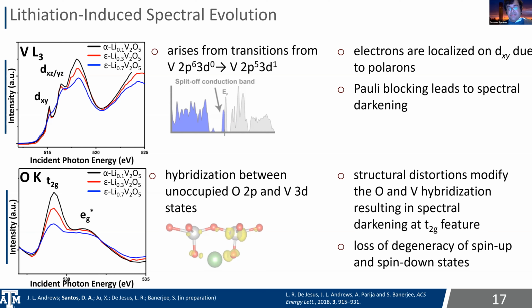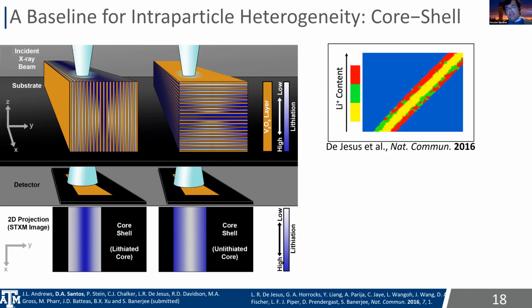And this then allows us to probe very finely the phase evolution as a function of lithiation and as a function of particle geometry in these structures. Okay, so here's an example. Depending on the orientation of the particle with respect to our focused X-ray beam, we typically will see a core-shell behavior where we've got an unlithiated core and a more surface-lithiated shell.